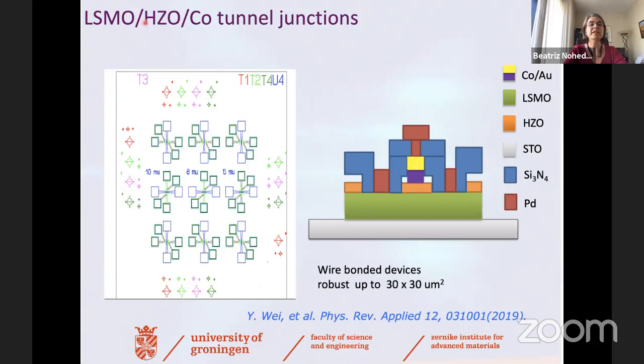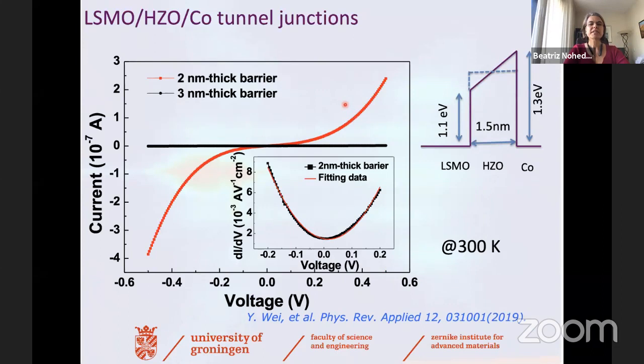And so we have made really extraordinary tunnel junctions with hafnia zirconia layers that are only 2 nanometers thick. And the devices are complicated, but basically the junctions are between a bottom electrode of lanthanum strontium manganite, a ferromagnet, and a top electrode of cobalt gold. You can see here, they really work like tunnel junctions, and you can see the difference between a 2 nanometer thick barrier and a 3 nanometer thick barrier. A 3 nanometer hafnia layer is so insulating that you cannot measure the current anymore. So this is a huge advantage of having materials like hafnia with a much larger band gap than normal ferroelectrics.